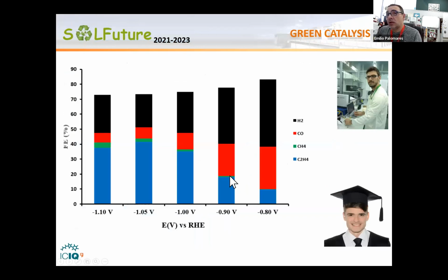And well, we connected them, and these are results we achieved last week with a master's student, Joan Marc, who is now doing the PhD, and a postdoctoral fellow who now has a position as a professor in Trieste. And here you can see, from CO2 and using a tandem solar cell based on organics and perovskite as a power source, we got quite nice yields for ethylene, for methane, some CO and some hydrogen. And the challenge is, of course, to reduce the hydrogen you form, which is difficult because the more current you need, the more hydrogen you produce. What is missing here to arrive at 100% Faraday efficiency is that this was measuring the gas phase, and we're still analyzing the liquids because we want to know the catalytic cycle. We have detected some formic acid, and we would also like to know where this formic acid is coming from.